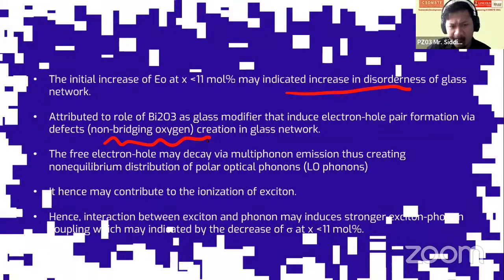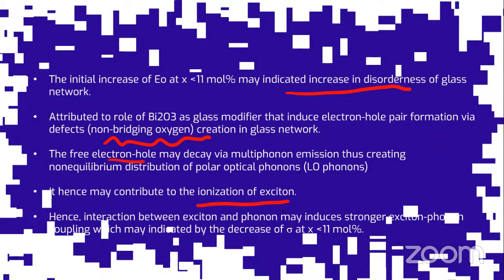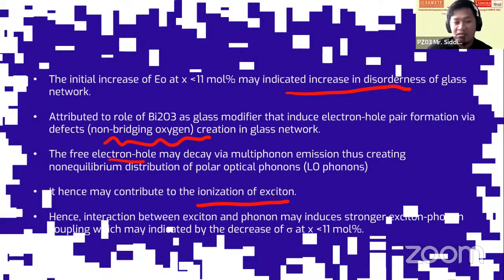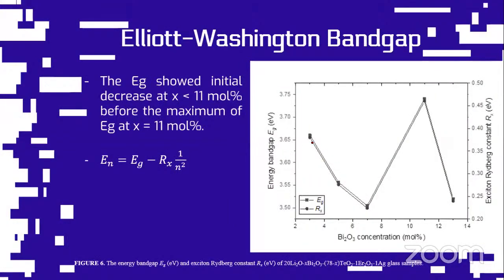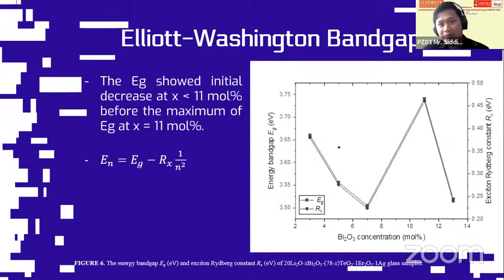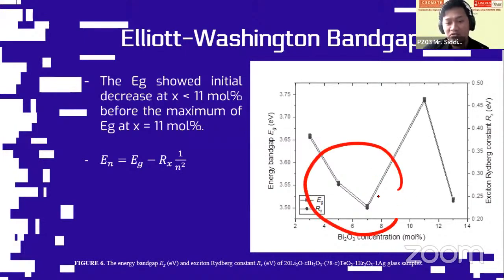So whenever we have a defect, it will create free electron-hole formation. The free electron-hole formation will decay via multi-phonon emission. The multi-phonon emission will help the ionization of the exciton. Whenever the exciton is ionized, we can have strong exciton-phonon coupling at this region. So you can see from here, whenever the exciton-phonon coupling is increasing and we have strong exciton-phonon coupling at the region before 11 mol%, we can also have a decrease in terms of energy band gap.